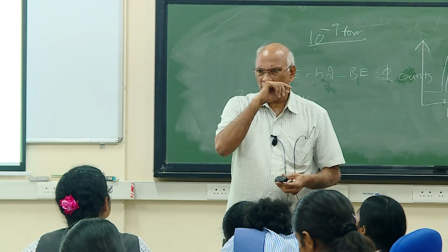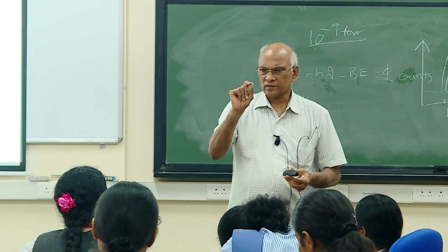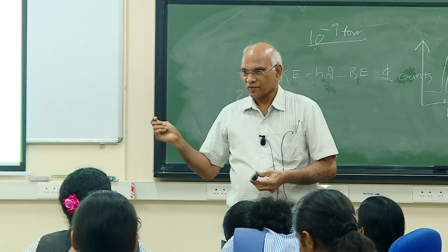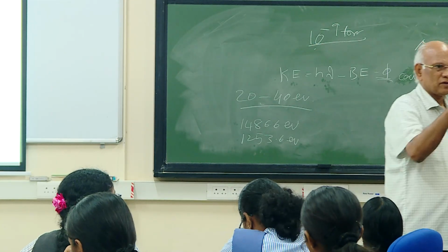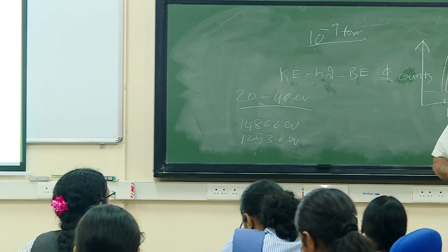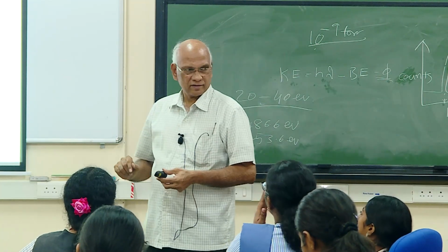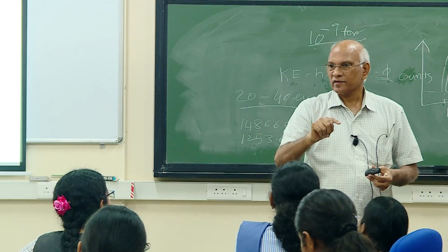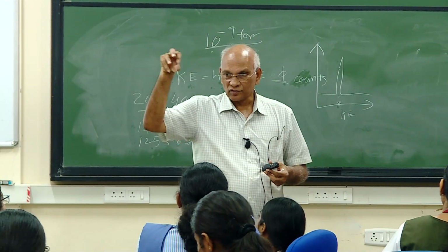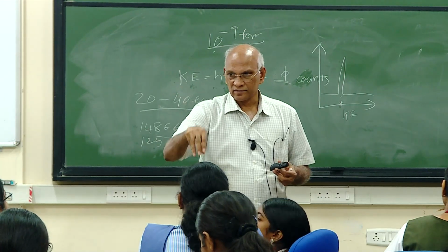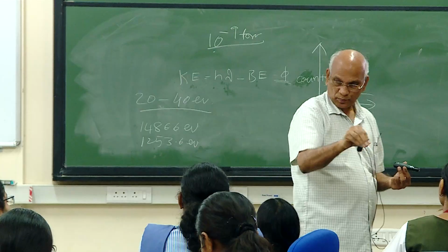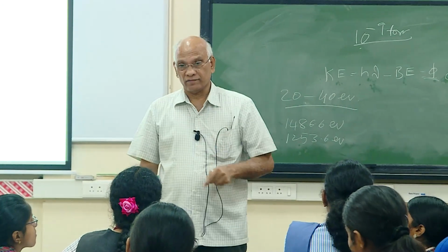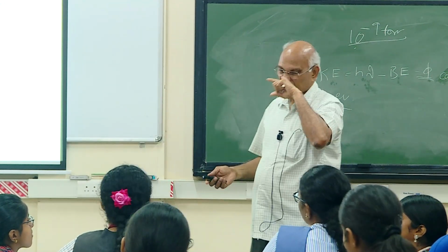Okay, all right. So suppose you take an atom. Its oxidation state is 0. I'm going to come back to that point. You are asking the questions ahead of what I am teaching. You have an atom with positive charge. Initially 0, atom valence, the charge is 0, then +1, +2, +3. So I remove an electron from one of the orbitals, one of the energy levels. The 0, +1, +2, +3 will not have the same value because of this. The charge is increasing, so the binding energy will increase because the nuclear influence is more, right? So if this atom is present in a compound with whatever oxidation state, then definitely it will get influenced. Then that is what is called a chemical shift. I will come to that point a little later. Right? Okay, I will come to that point quickly.